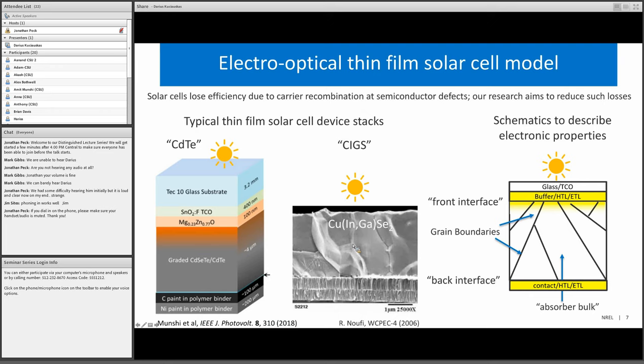Now, these are complicated structures with very many different aspects. For the analysis that I do for electro-optical characterization, I simplify these types of structures into the cartoon shown on the right. Here we see the two contact or buffer layers in yellow, the front interface that needs to be transparent, and the back interface that does not have to be transparent, although it could be. Then there are the grain boundaries, the regions between the crystalline grains in the material, as well as the absorber bulk. So we are trying to identify defects that are present in these specific device locations, as well as their impact on solar cell efficiency and reliability.